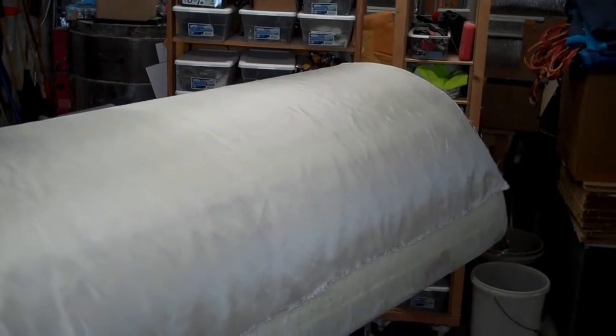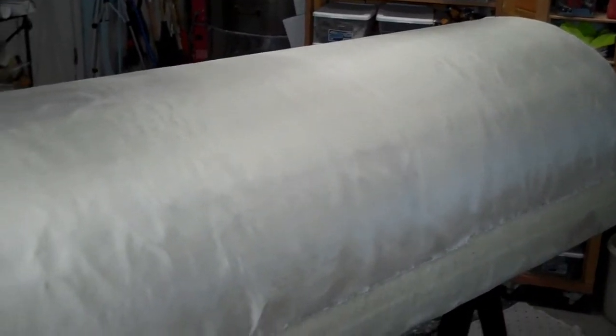I'm using a thin woven fiberglass as my last layer of fiberglass before my gel coat that's against the water. So this stuff flows around compound curves a lot nicer than chop strand mat does. It required essentially just one cut here to change over from the cylindrical shape to the conical nose cone and let this stuff here overlap. You can see it's sliding back and overlapping. Without that cut, it would have had a big wrinkle here. But with that cut, I'm pretty sure I'm going to be able to smooth that all down once I put